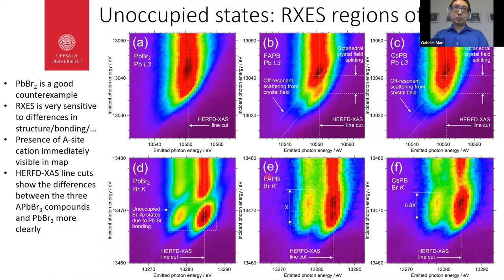So now we're going to look a little bit more at the differences in the near edge region for various compounds of interest. On the top row, these are all lead L3 regions of interest for lead bromide. Lead bromide serves as a really good counterexample to the perovskites because it's not a perovskite, it's not cubic. Figures B and C are for formamidinium lead bromide and cesium lead bromide, the two perovskites.